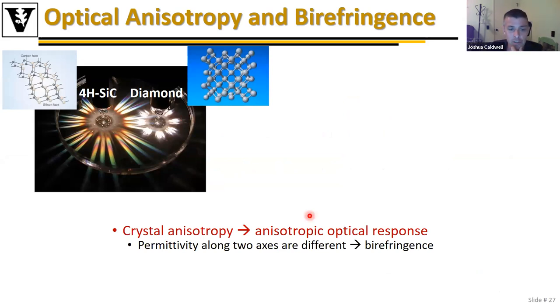To understand that, we're going to start with anisotropy in the crystal structure. Sticking with silicon carbide, you can see this anisotropic crystal structure, which means that light along one axis will propagate at a different speed than the other, and therefore the permittivities along those axes are different. I can compare that to diamond, where it's isotropic. And in the visible, 4H silicon carbide and diamond have roughly the same refractive index, on the order of 2.4, leading to this brilliance within gemstones that you ordinarily see.